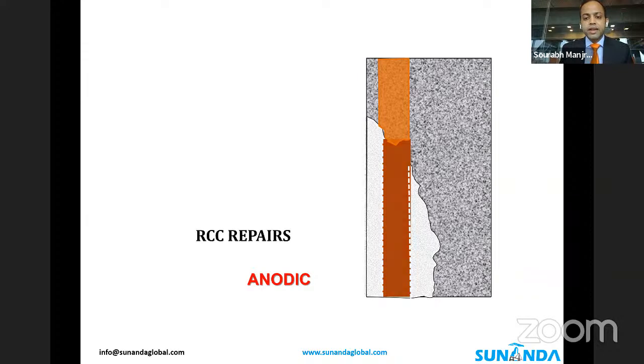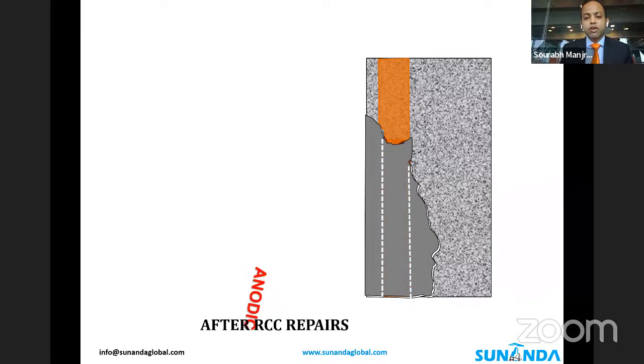After repairing this particular patch, things have changed. All of a sudden now this patch has become relatively stronger. And the embedded steel now is all of a sudden weaker or more anodic. And when corrosion strikes, it will always strike the weaker or the anodic part first. In turn, the embedded steel now will corrode faster than it should have or would have. Increase in diameter, transfer the stress onto the concrete, and you'll see a crack right there at the interface, and once again making the structure vulnerable to contaminants. So what can we do to resolve this issue?